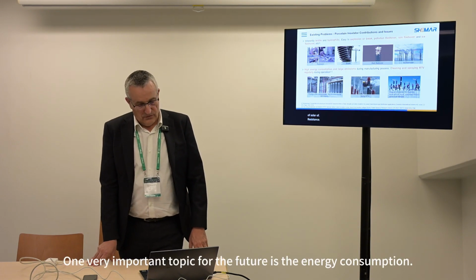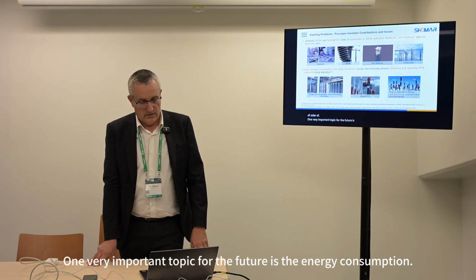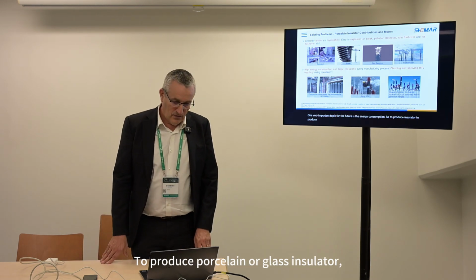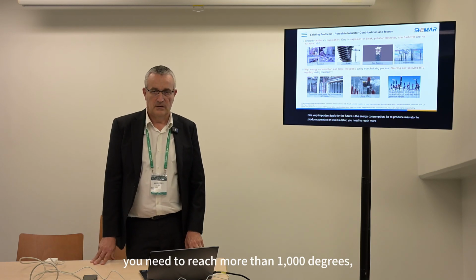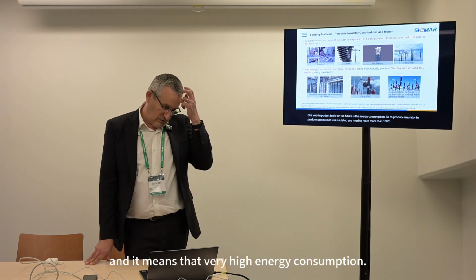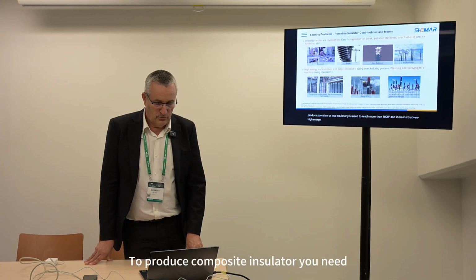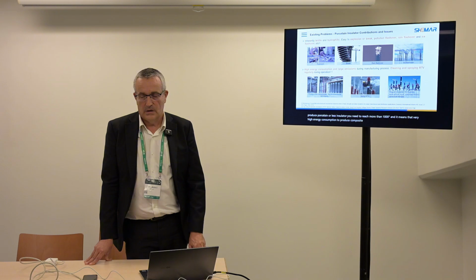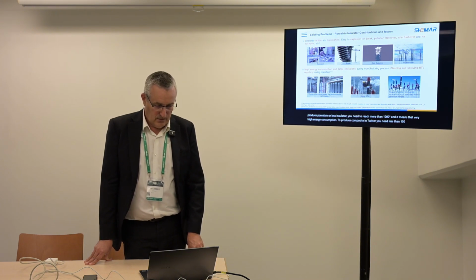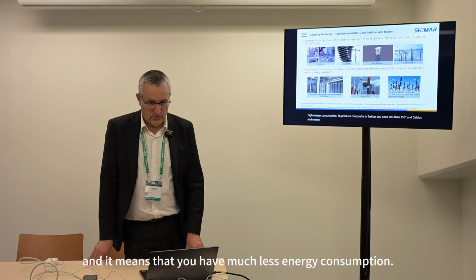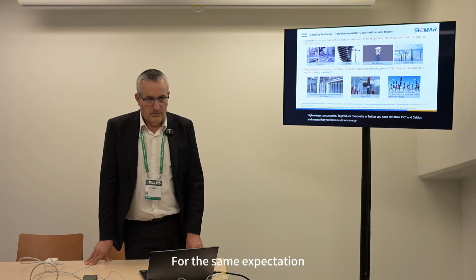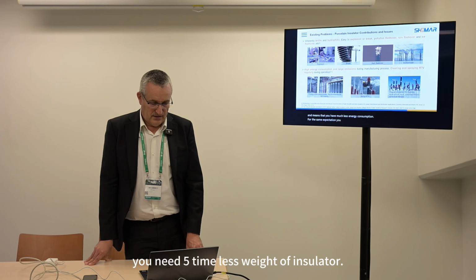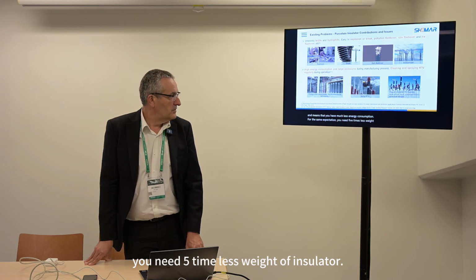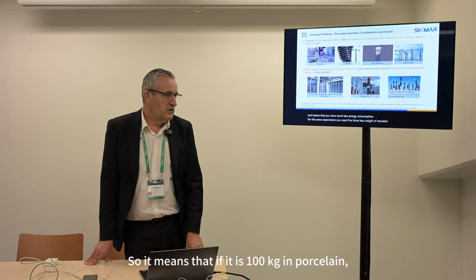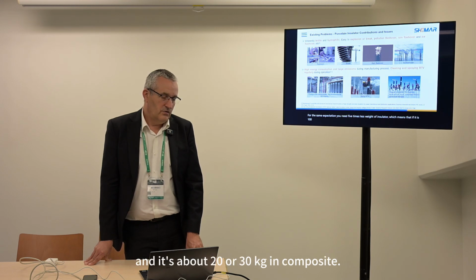One very important topic for the future is the energy consumption. To produce porcelain or glass insulator, you need to reach more than 1000 degrees, and it means very high energy consumption. To produce composite insulator, you need less than 150 degrees, and it means that you have much less energy consumption. For the same expectation, you need 5 times less weight of insulator. So if it is 100 kilos in porcelain, it's about 20 or 30 kilograms in composite.